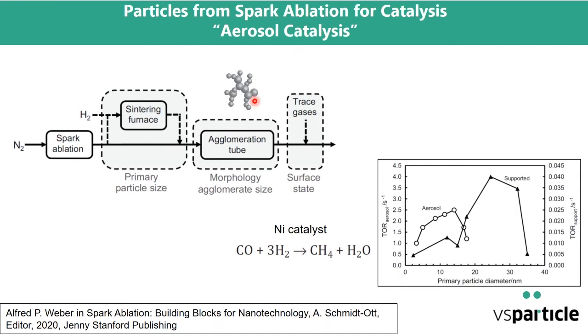But of course, the same screening method could also be used for any different mixtures, using different components. The fact that a nickel catalyst is still being used for this reaction shows that this mixing has hardly been used, that catalysts are still being used that consist of single elements. It means that the trillions of possibilities that we have in mixing have not really been used. It would be an incredible coincidence if the pure material would be better than any mixture.